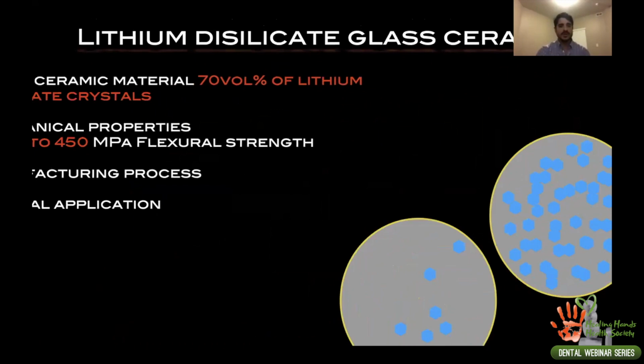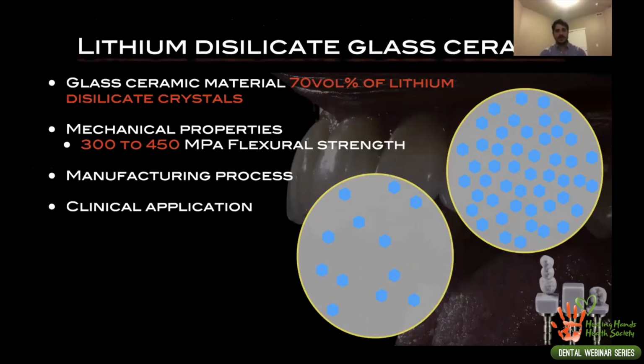If we move forward to the lithium disilicate glass ceramic though, now we have 70% of the whole material being filled with lithium disilicate crystals. And then it makes the mechanical property jump from 300 from the feldspathic to 450 megapascal of flexural strength. And why is that? Why is the lithium disilicate not as translucent as the feldspathic, and why do the 70% of lithium disilicate crystals make it so much stronger?